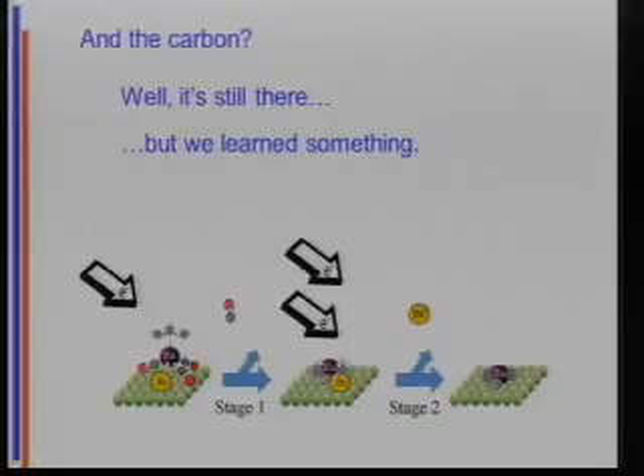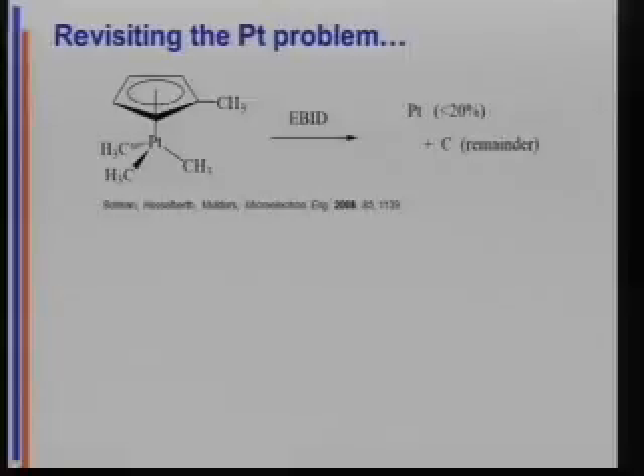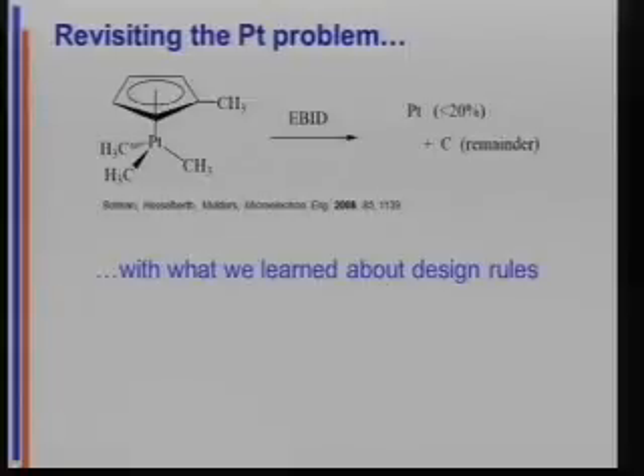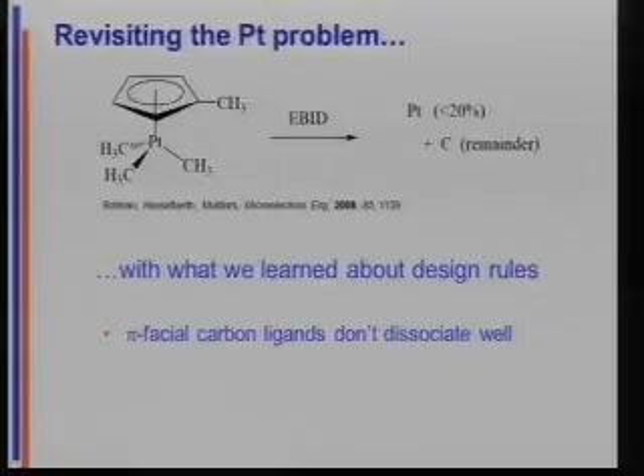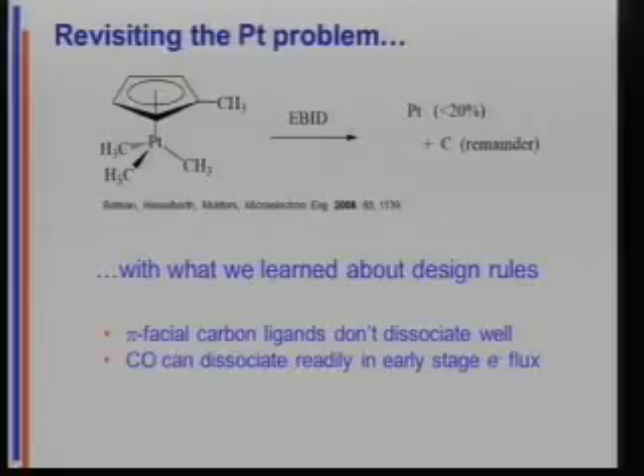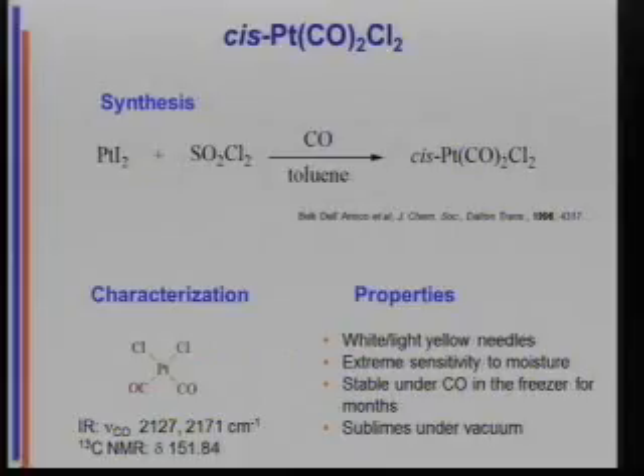So let's go back to that platinum problem. Okay, the platinum problem, that platinum problem. But we know the CP is a disaster. COs work. Halides work. Let's be inorganic and organometallic chemists for a minute. So here's a very old compound that had never been looked at for EBID. Okay? And so we made this compound. It turns out to have the right physical properties. It's very volatile. It's stable enough. So far, so good. So we do the experiment.